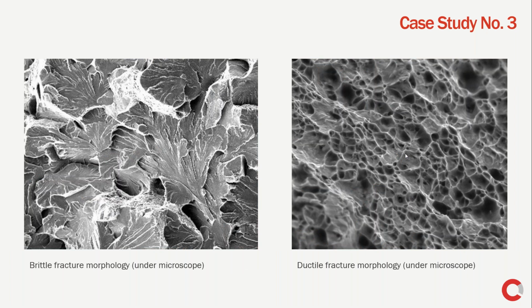It's fascinating, actually. On the left, you can see the fracture morphology of a brittle fracture, and on the right, that of a ductile fracture. The main difference is, when we're talking about a material that's supposed to behave ductile and absorb a lot of energy, say during impact or bending or flexural loads, but instead of failing ductile, fails brittle, that is because it was operating under temperatures below its ductile to brittle transition temperature.